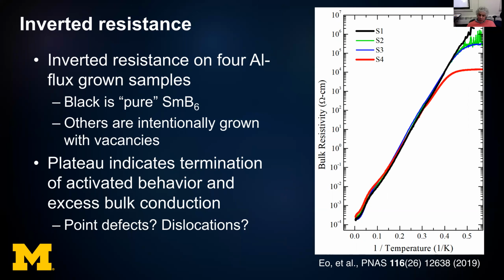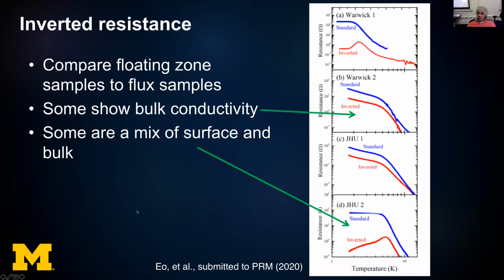Now, we will extend these measurements to the floating zone set, and here is the raw data. And when you look at it, the 2 samples which we mentioned earlier indeed appear to be bulk conductors. We don't see this inverted resistance going down. For 2 of them, the plateau is definitely due to surface, and we do extract bulk conductivity using this method.